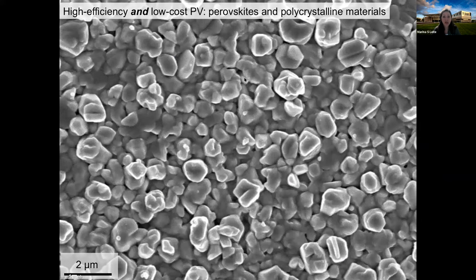So let me show you one of the key points that intrigued us before we started working on perovskite solar cells: the fact that we're not dealing with epitaxial materials. And I know folks at FMG have a lot of work on epitaxial semiconductors, right? But if you're dealing with polycrystalline and bulk materials that are low cost, if you take a closer look, we can see that they're formed by a lot of grains that have interfaces and defects. So at the time, and it seems to be the case, it had been reported that by far the highest power conversion efficiencies occur in materials that are epitaxial.